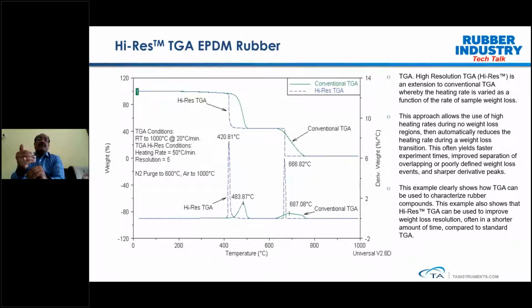So in this case, though we started off the heating rate initially at 50 degrees centigrade per minute, as soon as the sample reaches the initial weight loss, which is observed around 420 degrees centigrade, the heating rate will be completely reduced, which allows the kinetics to complete, and we allow the sample to totally decompose, and that will give a sharpened weight loss. Afterwards, once the weight gets stabilized and your derivative comes close to zero, the heating rate kicks in again and goes to the higher range. Finally, we go to the next level of decomposition. This way, we are resolving the overlapping events, and that also helps us to quantify each weight loss in a better manner, which could be complicated in many standard runs. This is the clear advantage of the high-res TGA.